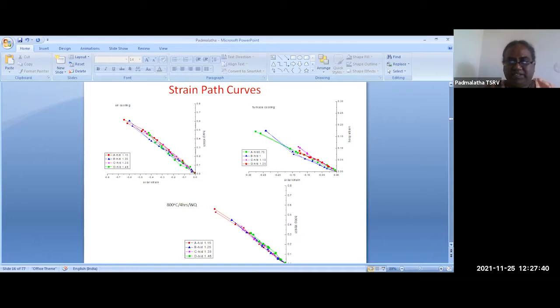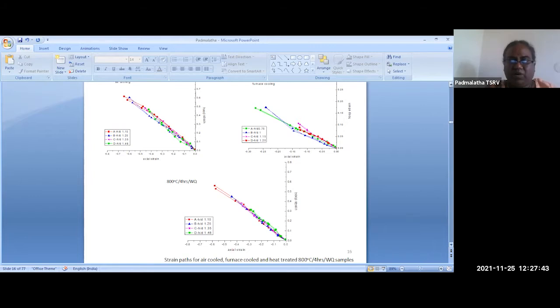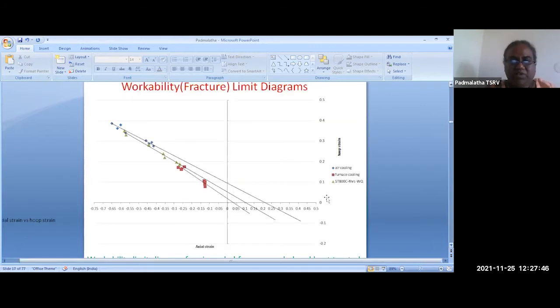If we plot all the fracture points for all the different conditions, we'll generate a workability limit diagram like this. Many points are overlapped. So if we plot the fracture strains for all the different fracture conditions, we'll get a workability limit diagram. We have generated the workability limit diagram for 3 conditions: air cooling, furnace cooling, and aging condition. And we have seen that for air cooling, the workability is better compared to the other 2 conditions.